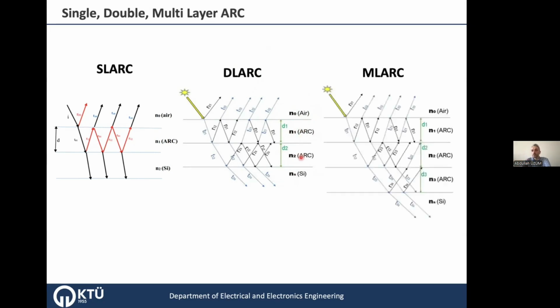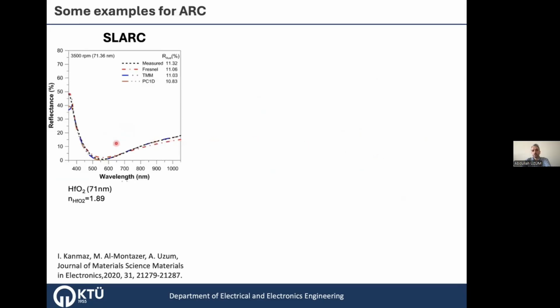Or you can do multi-layer anti-reflection coatings, and in this case, again, you can calculate it with different techniques, with the transmitted and reflected lights for each case. Here I show you some examples from our previous works. For example, hafnium oxide as an anti-reflection layer on the surface of silicon. This is the measured value, around 11%, and these are the calculated and simulated values, which are very similar, so you have almost zero reflection around the peak of the solar spectrum.